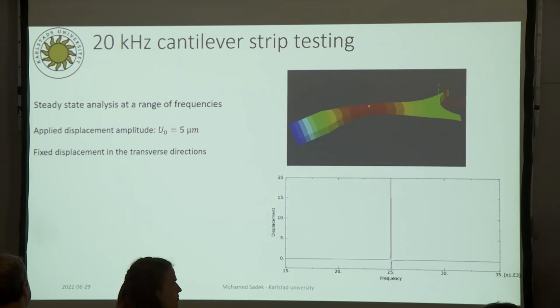And we did that at a range of frequencies from 15 kHz up to 35, and we could see that the peak is at 25 kHz, exactly the frequency of the specimen that I showed you in the previous slide. But anyway, the test will be run at 20 kHz, and this is the value that should be the realistic value, 9.4 micrometer. This is the displacement of the yellow point here in the middle of the specimen.